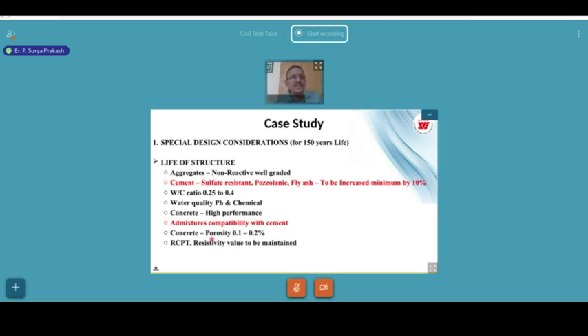So the first and foremost is aggregates. The aggregates have to be non-reactive. So test for non-reactive aggregates. That means they have to be inert as much as possible, preferably granite. And then they should be well graded. Next is the cement. It has to be sulfate resistant, preferably pozzolanic, and fly ash to be increased, and content can be increased minimum by 10% from the design requirements. Water cement ratio maintain between 0.25 to 0.4, and water quality pH value, try to maintain, though the code allows you 6 to 9, better maintain pH value of around 7, and then minimize the chemical content in